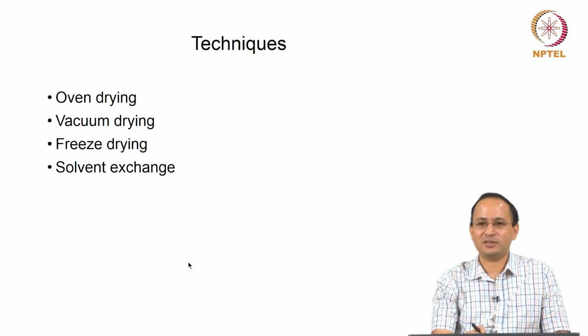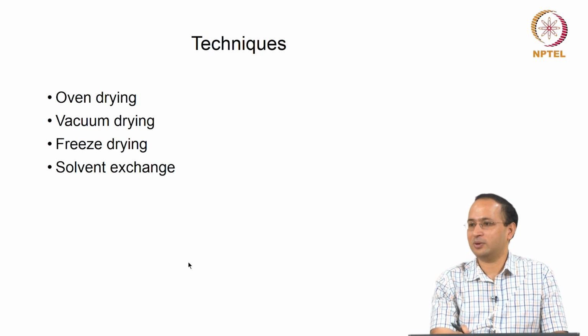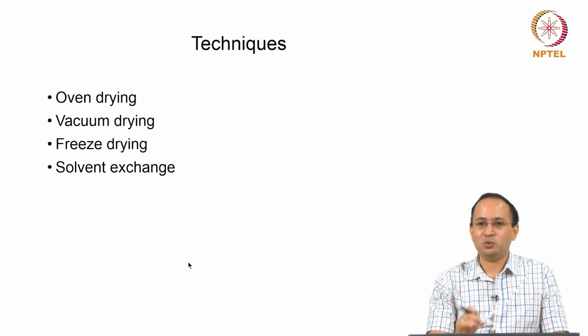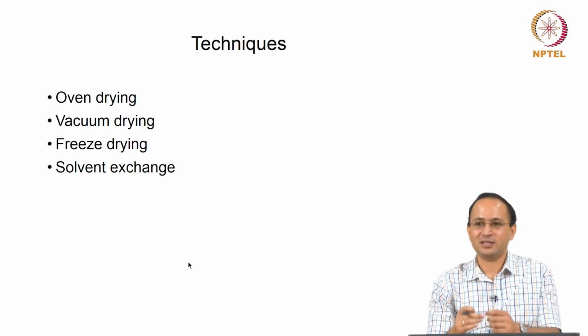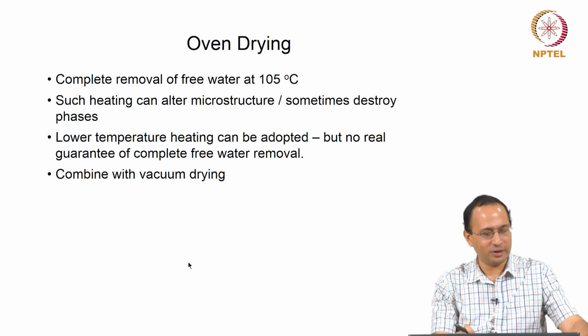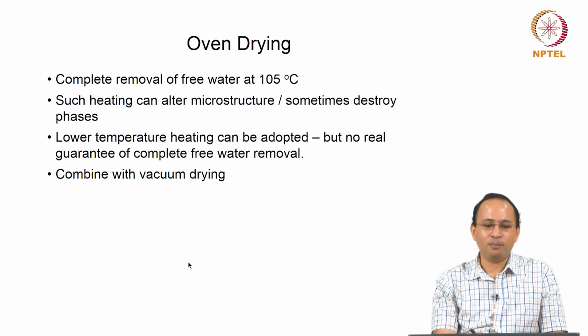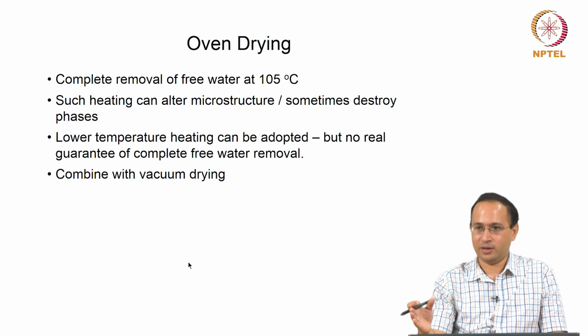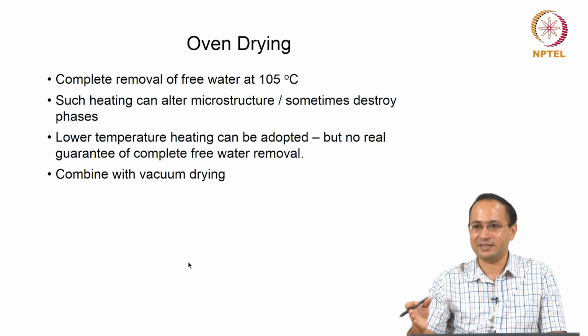How do you remove it? One of the simple things that comes to mind is, why don't you heat it up, right. So oven dry. Vacuum dry is you put it in some vacuum. Freeze dry, you freeze the water, then let it sublimate. Solvent exchange is you are using some solvents which are miscible with water and then let it evaporate. We will go over it. So oven drying is complete removal of free water at 105 degrees Celsius. If you treat your samples, cement paste, concrete at 105 degrees Celsius, then you will remove the capillary water.